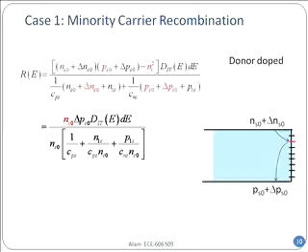NP is Ni squared, N is 10 to the power 18, Ni squared is 10 to the power 20. I have 100. I have 100 of the other type of carrier. So think about it: 10 to the power 18, 10 to the power 2. Which one is bigger? That is how I drop that PS naught term, because it's 100 compared to 10 to the power 18.